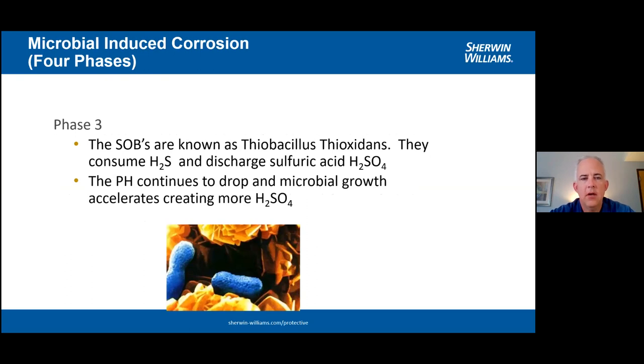So let's go to phase three. The sulfur oxidizing bacteria are known as Thiobacillus thiooxidans. They consume hydrogen sulfide gas. They're eating what is naturally occurring in our system. They're eating this hydrogen sulfide gas, but the problem they cause is they discharge a sulfuric acid. They excrete sulfuric acid. Sulfuric acid, as we know on the pH scale, as it lays on that concrete, aggressively drops that pH. It's very aggressive and it brings that pH down. I've been in concrete structures and seen a pH of 4 before on a wet well where we had a strong hydrogen sulfide gas presence. This pH continues to drop, microbial growth accelerates, and it creates more sulfuric acid. Sulfuric acid is the true enemy in the wastewater treatment and also the sewer collections industry. That's what's destroying our concrete.